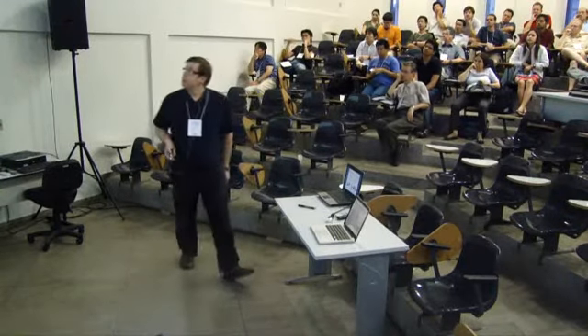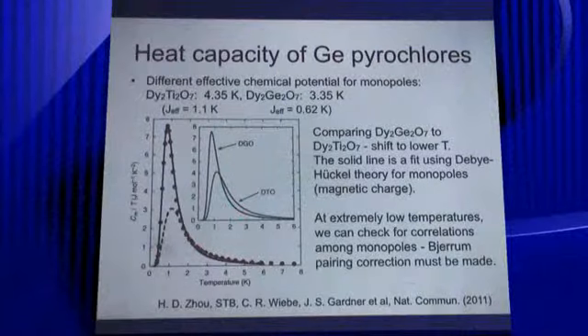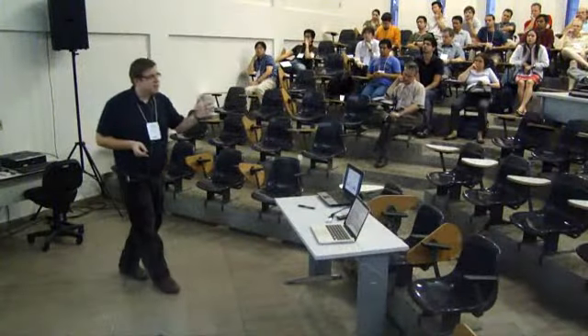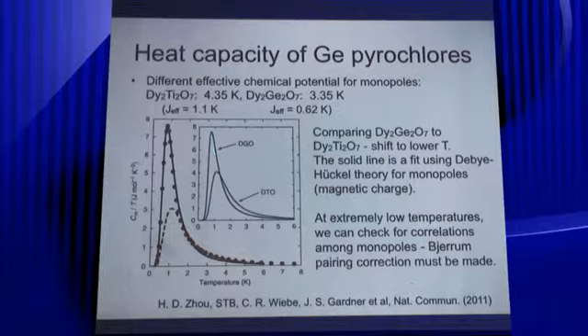So here's the heat capacity of germanium pyrochlores. We're comparing this in this plot here, the dysprosium germanate versus dysprosium titanate. And this is actually predicted by den Hertog and Gingras: when it shifts to lower temperatures because of lower chemical potential, you get a sharpening of this function here, and eventually it should reach this first order transition where you go to an antiferromagnet, right? But this is just comparing these two and seeing what they look like.